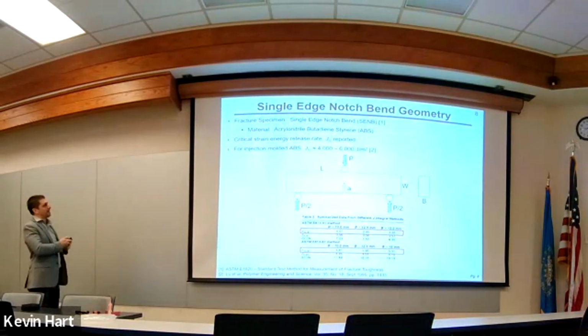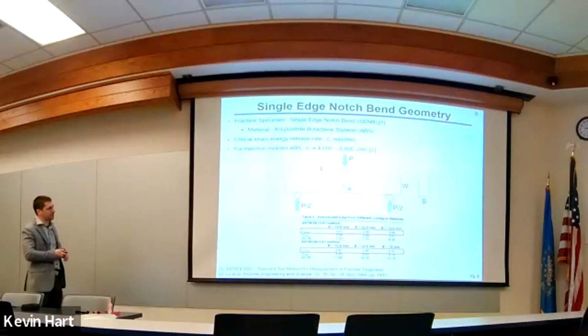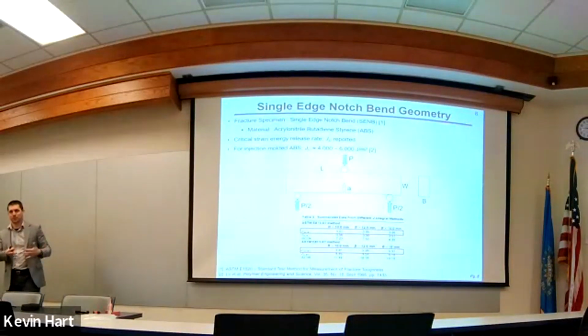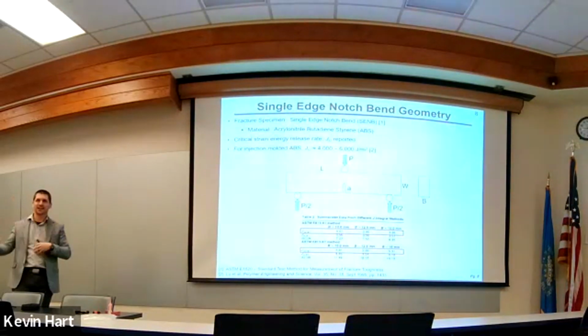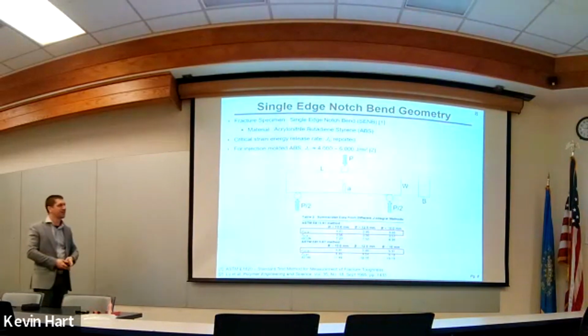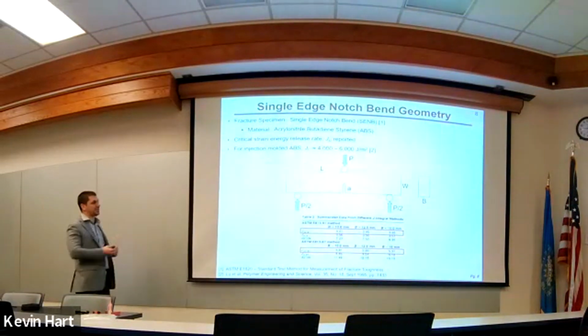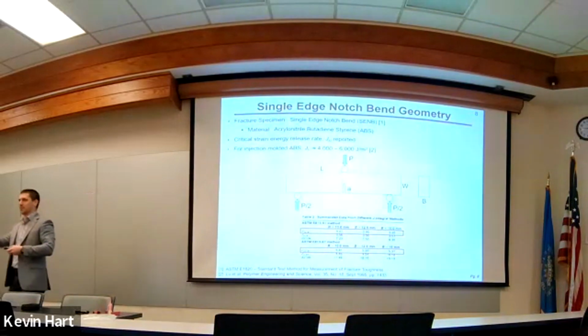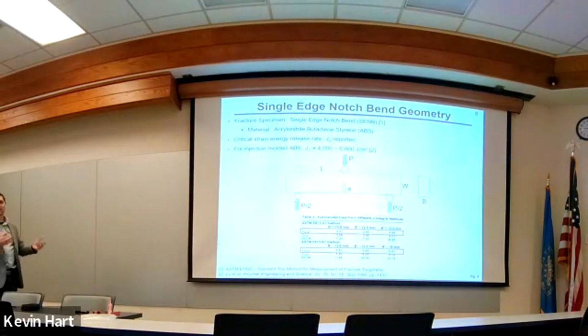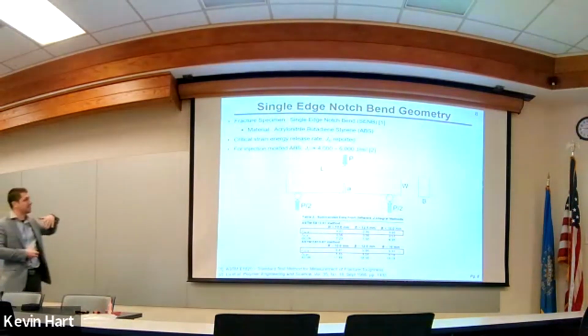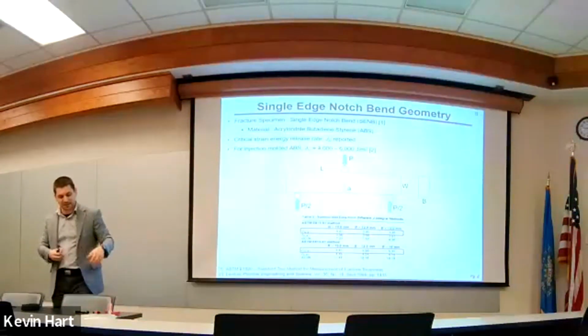Not important, but the idea is that we're going to measure this critical strain energy release rate, J1C here, and the units you can use to understand what this is, joules per meter squared. This is a measurement of energy in joules required to create a crack of a certain size, meter squared. So how much energy does it take to create a crack of a certain size, meter squared? So for a typical injection molded ABS, like a normal polymer that you might use for injection molding, this J1C value is a material property, a lot like stiffness. You can measure this using a sample that looks like this, and this particular ABS that we're going to talk about is in the range of 4,000 to 6,000 joules per meter squared.